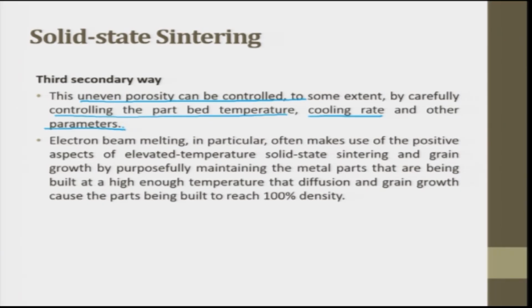Electron beam melting, replacing the laser by an electron beam, in particular often makes use of a positive aspect of elevated temperature solid state sintering and grain growth by purposefully maintaining the metal parts that are being built at a high enough temperature that diffusion and grain growth cause the part to be built to 100%. Thank you very much.